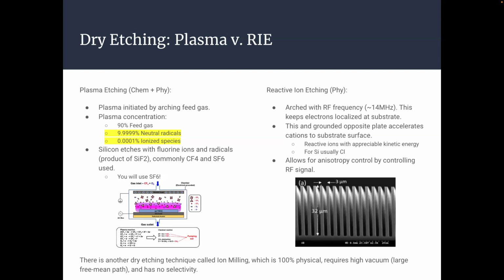So for reactive ion etching, the main use for silicon is anything with a chlorine atom in it. They'll sit around the surface the same way fluoride does, but now those accelerating cations will come in, disrupt that SiCl chemisorption, and we'll get removal of them together as a volatile gas, as said before. Here you can see just the anisotropic nature of it. You can see the aspect ratio of this trench being 32 to 3, so about 10 to 1.